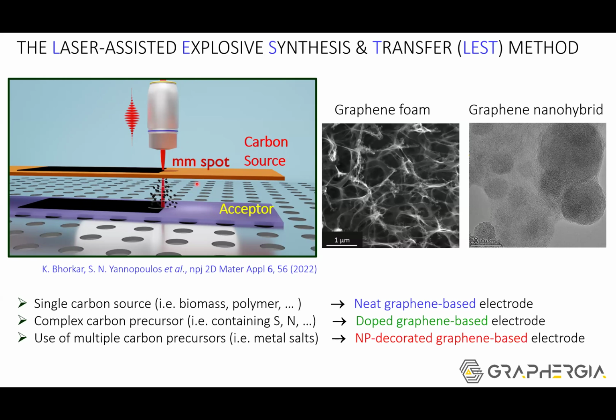In the way we developed this technique, we can produce graphene on different substrates, and the acceptor can be chosen across a wide range of materials, from textile or polymer to glass or even ceramic. The form of graphene, as you can see here, is three-dimensional, foam-like. This is very useful for energy storage applications, and depending on the carbon source and the additives applied to it, one can, in the end, also obtain graphene decorated with various types of nanoparticles.